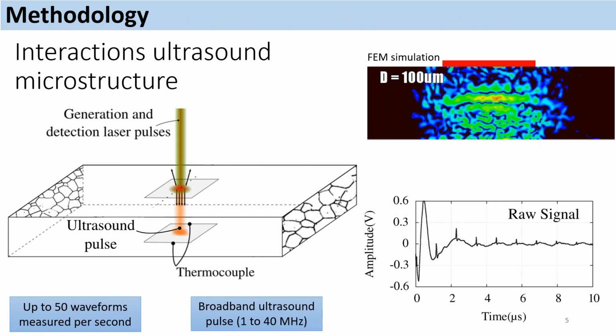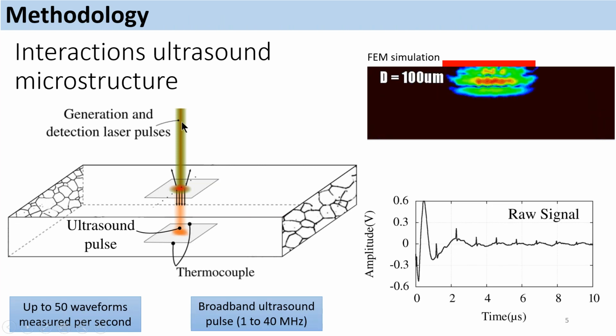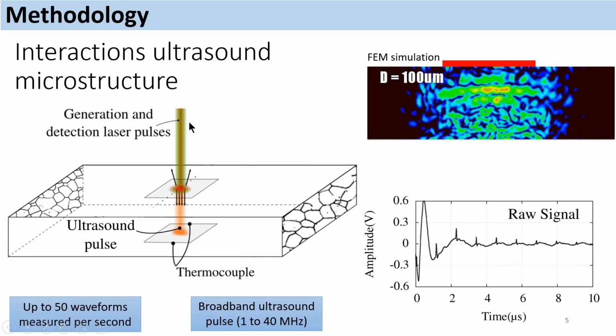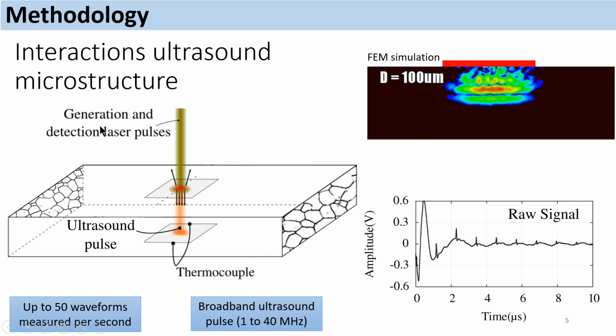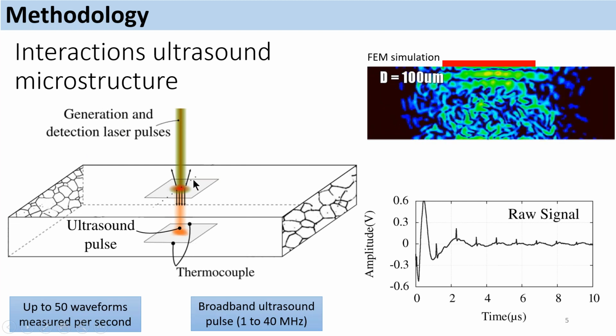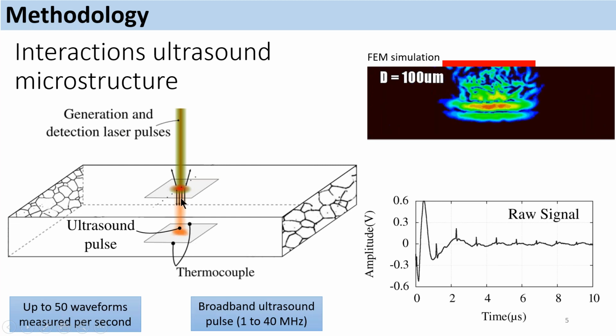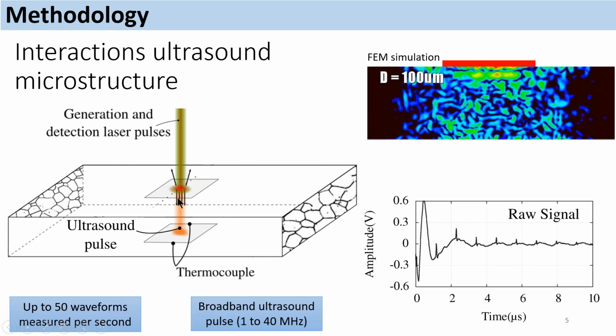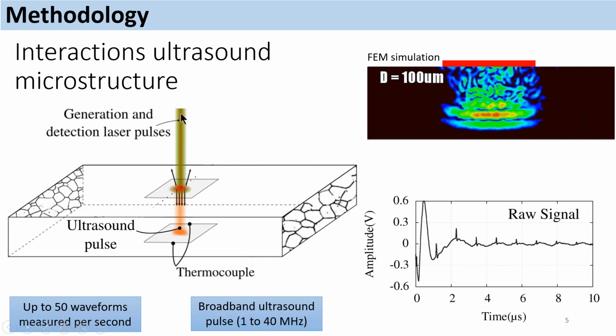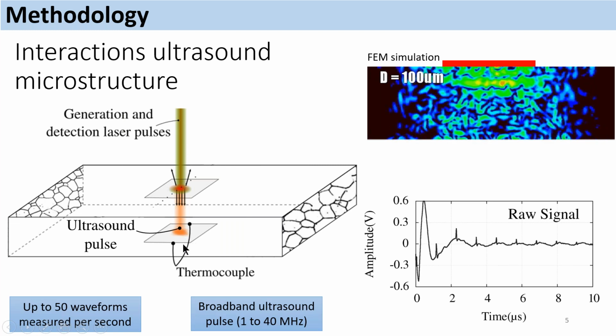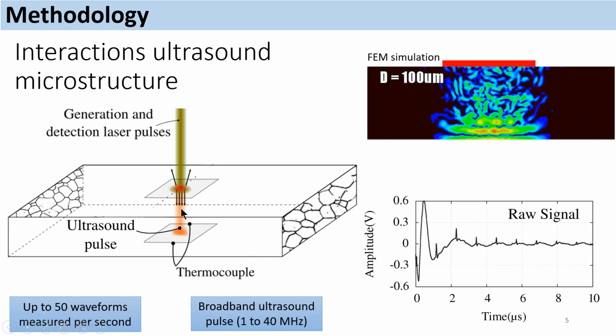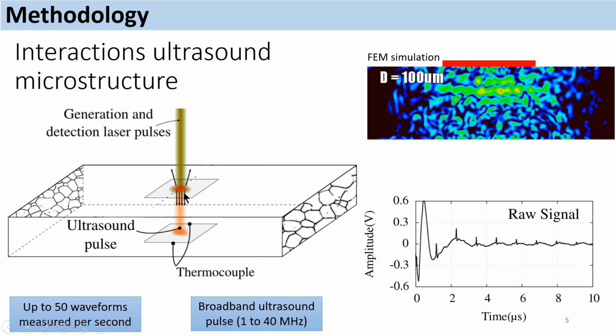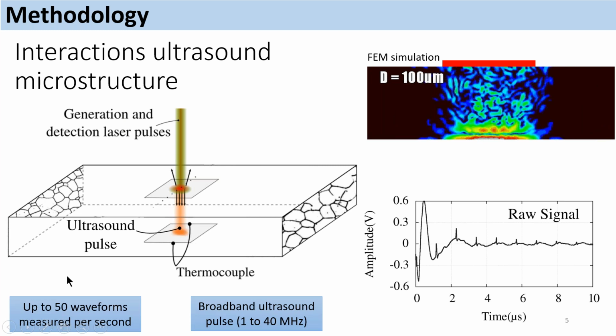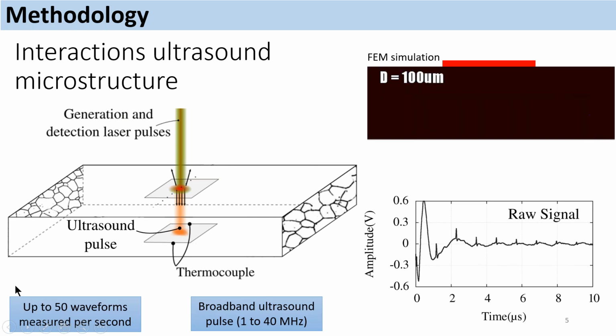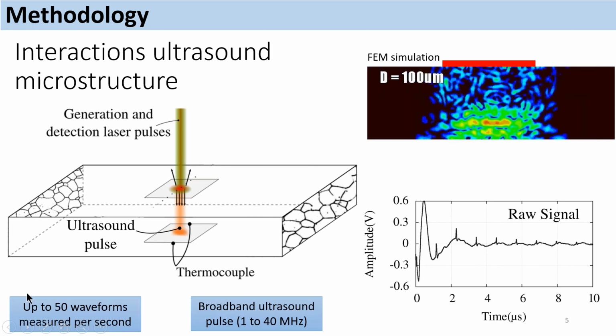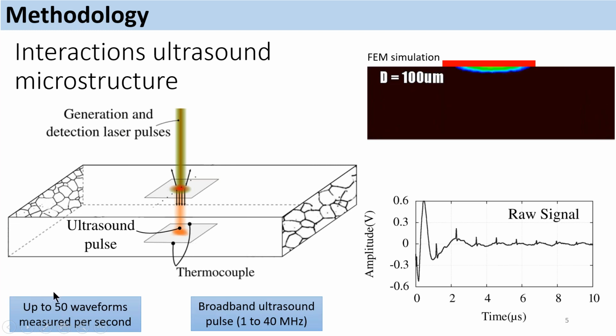So here is a detailed, schematic view of the different processes occurring during the measurement. There are two different lasers: one generation laser, which generates the pulse inside the microstructure, and a detection laser, here in the infrared domain, which looks at these ultrasound pulses arriving back at the surface of the sample. This system features the capability to acquire up to 50 waveforms per second.